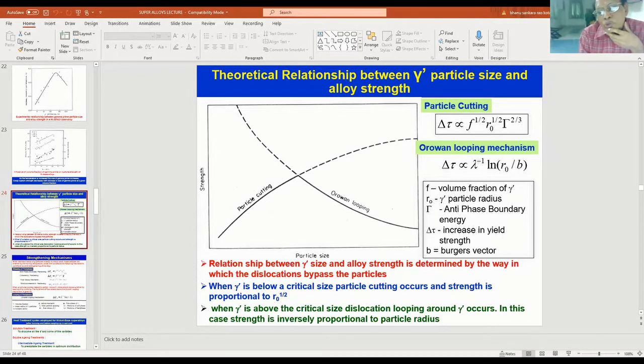When you go to very high particle sizes, the gamma prime will be looped. That is, it will be bypassed by looping. It will not be cut. Once the particle is cut, then coherency and all those things will play a very important role. Here, when the particle is cut, you see that your strength increase will depend on volume fraction and particle size.